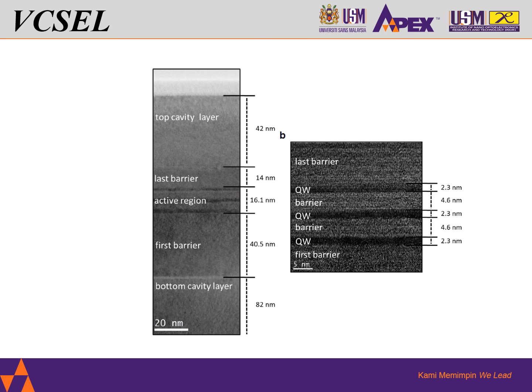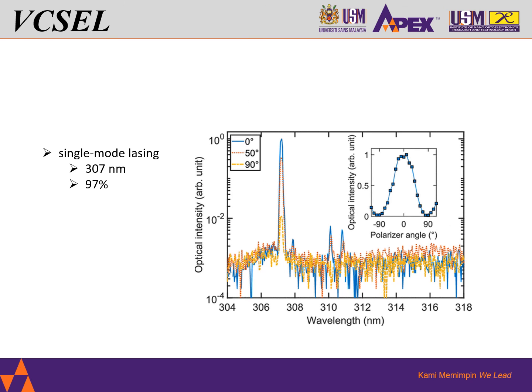And so this is the figure of the emission that showed single mode lasing. The single mode lasing peak is at 307 nanometer with a resolution limited linewidth and a degree of polarization of 97%.